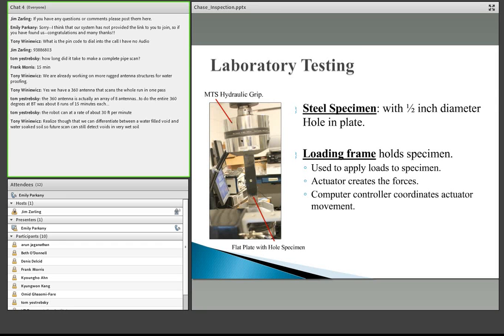The laboratory testing was very similar to what we did during the proof of concept, where we essentially evaluated the ability of the system to extract thermoelastic signals from specimens, but during this phase we loaded the specimens with random loading as opposed to nice sinusoidal loading.